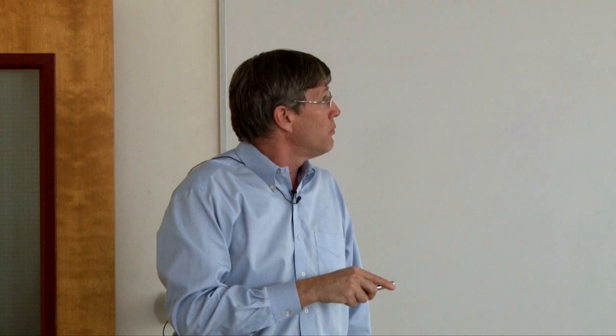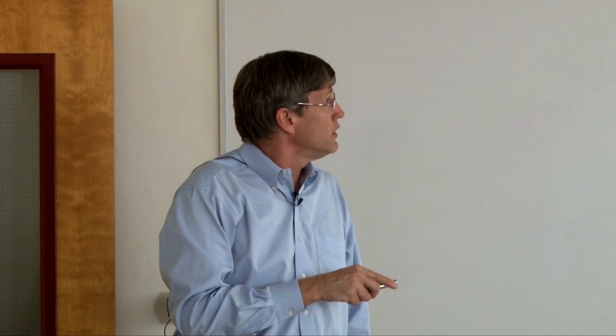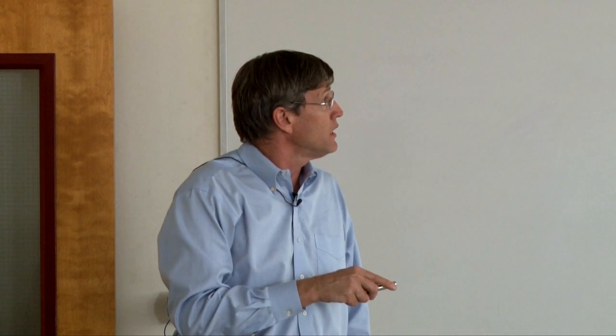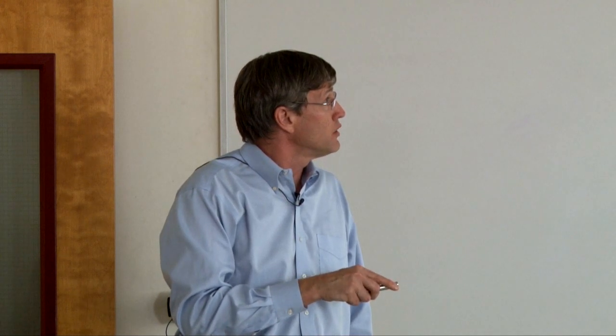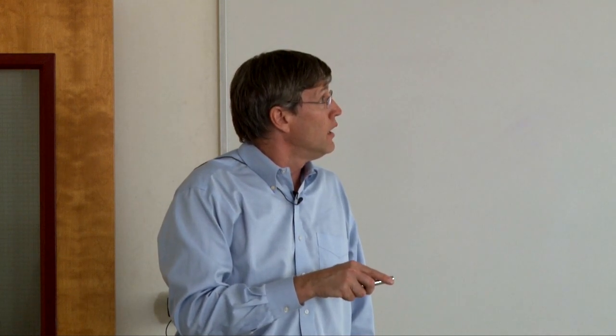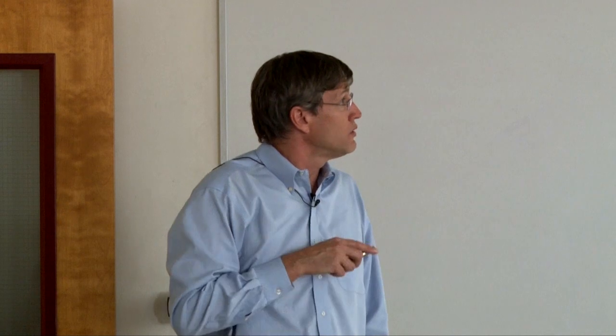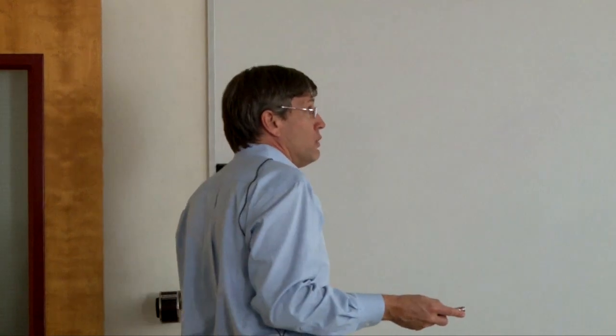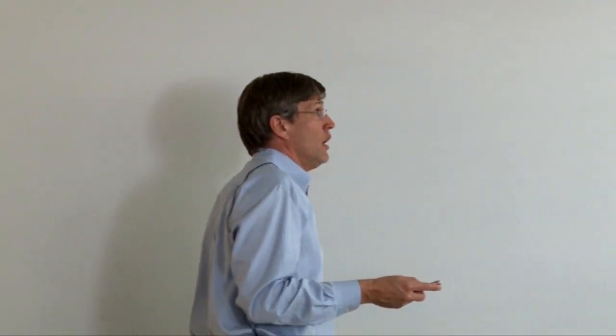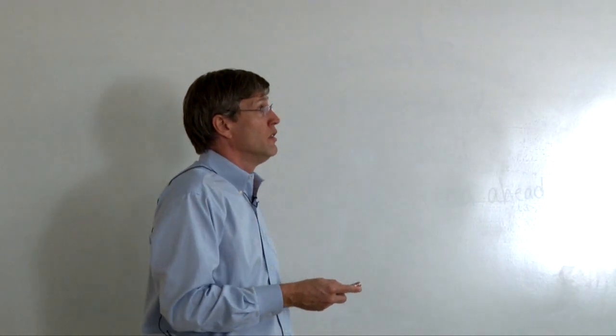Here's our platinum carbon. We can see this is a higher current. When we normalize that for the area of platinum at the surface, we're very high. The mass activity is not quite as high, but we're actually the best unsupported catalyst without carbon that's ever been reported that we're aware of.